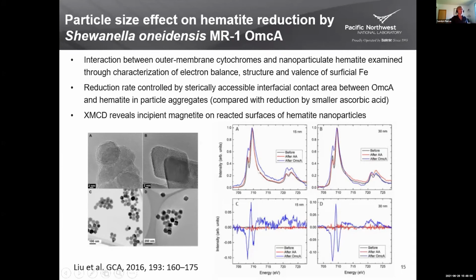This work was also really nicely showing the effect of aggregation of particles, and so the smaller particles aggregate more effectively, and the OmcA cytochrome was too large to access the iron in the aggregates. But once you got to a size range of about 30 nanometers, the aggregates had sufficiently large openings that the OmcA cytochrome could get in and access the available iron within the aggregates.